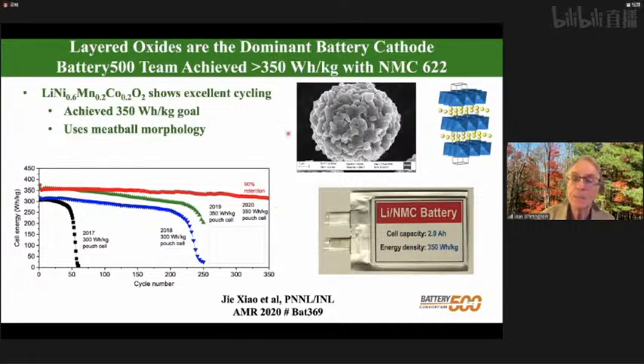The morphology of these materials I show you here, these are about 100 to 200 nanometer primary particles, and the secondary particles are about 5 to 20 microns across. And we use this, what we call meatball morphology, to get good packing. Here's the typical cells we make. They're about 2 ampere hours. And there's Jie Xiao at Pacific Northwest National Lab, who's responsible for making these cells. Then she sends them to Idaho National Lab for the actual testing. So on a volumetric basis, these are about 700 watt-hours per liter.